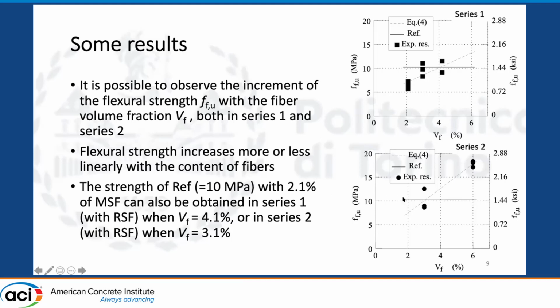And with respect to the reference composite, which has a strength equal to more or less 10 megapascal, we can reach the same strength with series 1 when the content of fiber is more or less 4.1 here. And on the contrary, in series 2, we can reach the same strength of the reference system when the content of fiber is 3.1. So in practice, we can have three composites with the same properties or the same strength. The reference, series 1 with 4.1% of fibers, recycled steel fibers, and series 2 with 3.1% of recycled steel fibers.